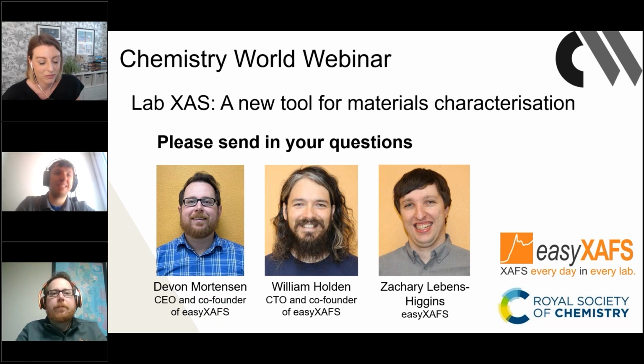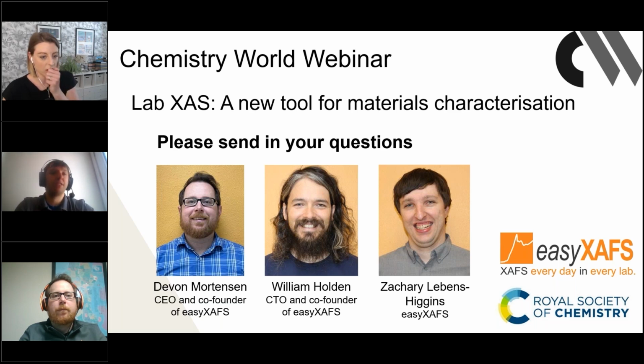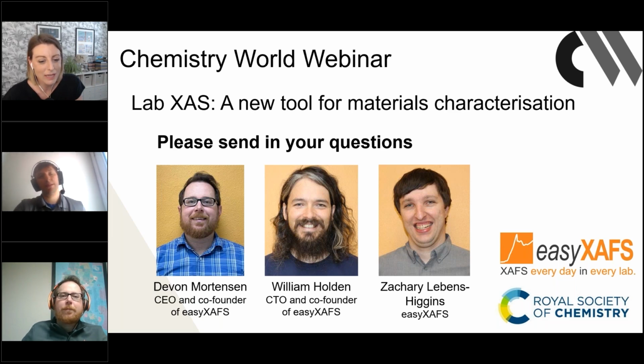So yes, basically the first row transition metals are in an optimal energy range. So those are where our instrument has the highest flux, and will be the quickest to measure. As you get to the 4D transition metals, particularly later in the 4D row, like ruthenium and palladium, those are at pretty high energies, like 20 to 25 keV, and our flux is a bit lower at those energies. So those measurements will typically take longer, on the order of a 10-hour measurement, because we're at such a high energy versus the 3D transition metals. Okay, thank you. I think that's answered that perfectly.